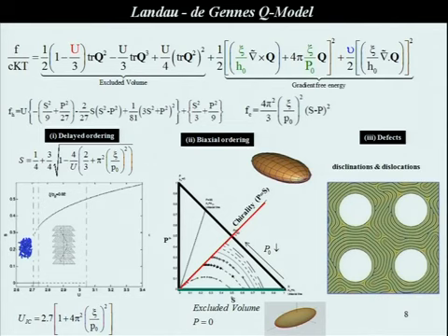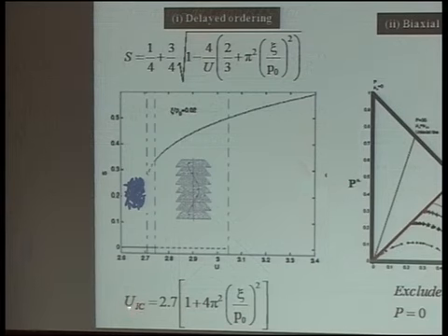In this formulation, we simplify and just look at S. This graph shows the effect of P0 on S. So the free energies are similar to the nematic. You have metastability of the isotropic phase, metastability of the nematic phase, but we have an effect of P0. This is the value of the concentration of the transition. When P0 is infinity, you recover the 2.7 from Maier and Saupe, etc. And when P0 is small, this concentration increases.